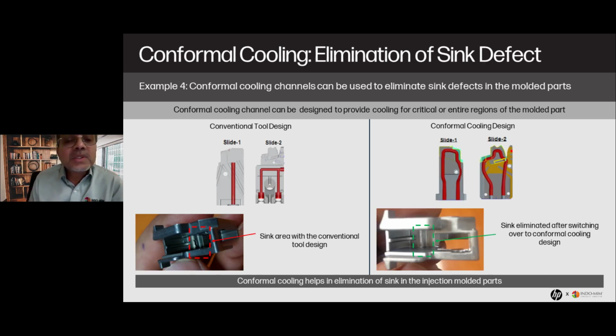The same thing applied to the elimination of the sink defect. As we all know, if the component has a lot of hot spots when you are molding, that results in a sink, and then eventually a void created because of the sink. Those kinds of defects, we were able to completely eliminate. If you see here, on the conventional slide you were only able to drill straight holes, but on a conformal cooled slide that was 3D printed using the binder jet process, we were able to take the cooling channel all the way to the surface of the molding. The kind of sink that we used to see all the time, by changing the mold design and method of mold manufacturing, we were able to completely eliminate on the component.